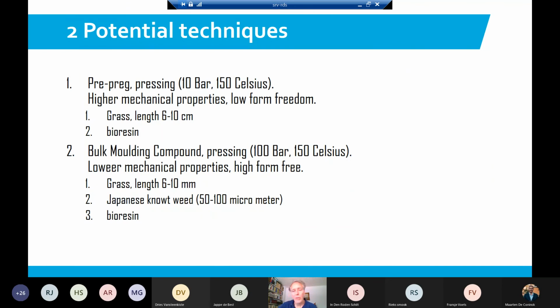There's two potential techniques if we want to use grass fiber and make this knuppelpad, a plank out of it. And technique one is prepregging. And what you do for prepregging, you mix longer fibers, say grass fibers are 6 to 10 centimeters. You mix them and needle punch them. That was in the previous presentation. It was being shown that they did in Germany a prepregging of these fibers into a mat, a non-woven mat you call it. Then you have to put this non-woven mat through a bath of resin and then get rid of the extra resin and compress the element in a product.